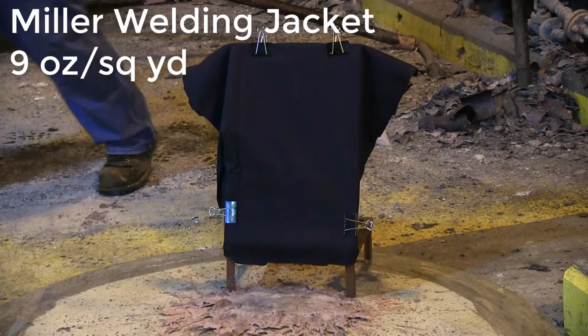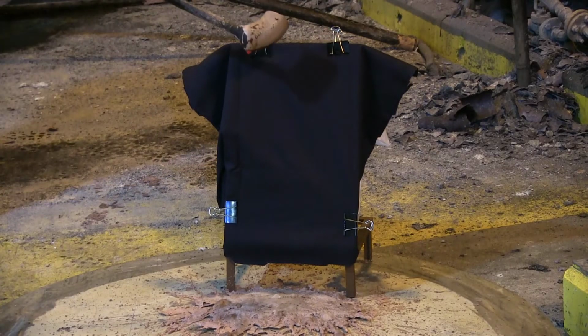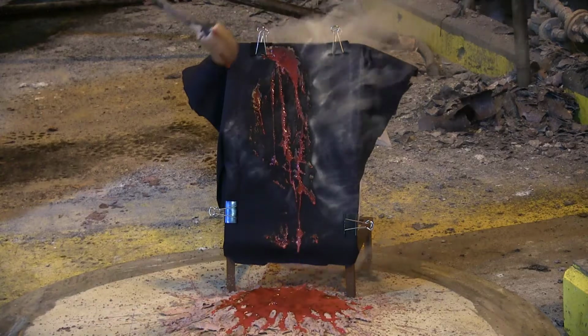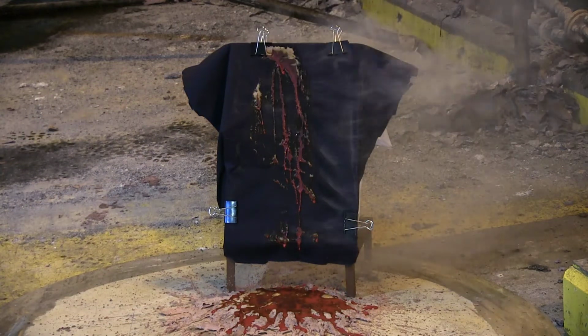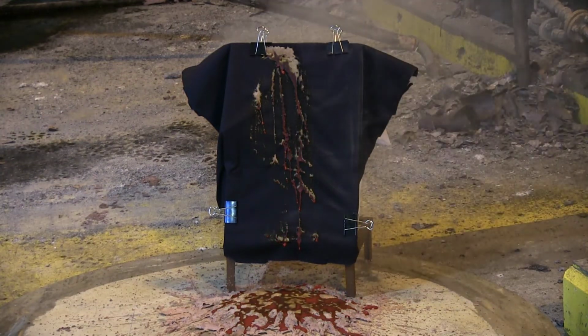The sixth material tested was a Miller welding jacket. Its composition is unknown. It is most likely comprised of a majority of FR7A treated cotton. The fabric does experience slight shrinkage as the smelt adheres to it.